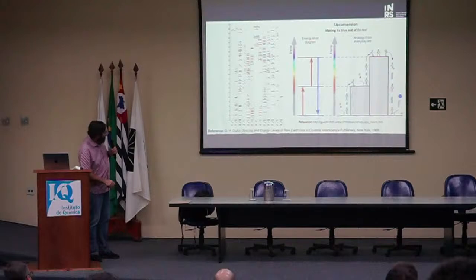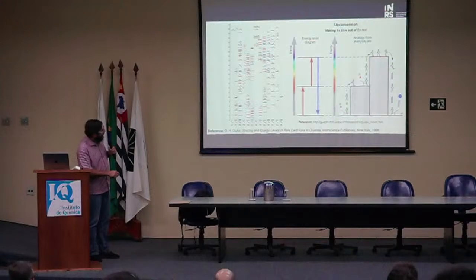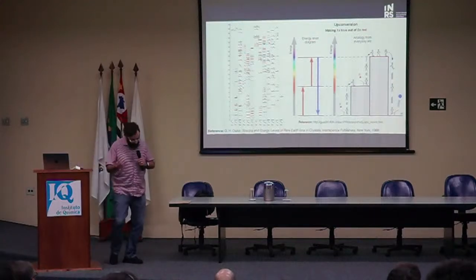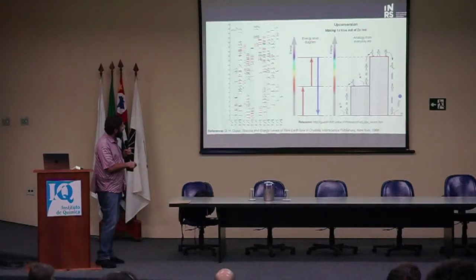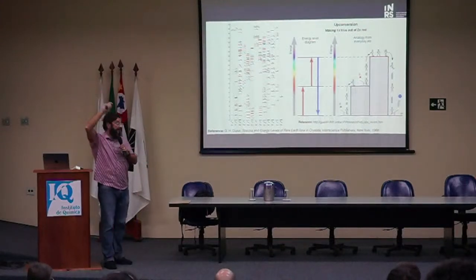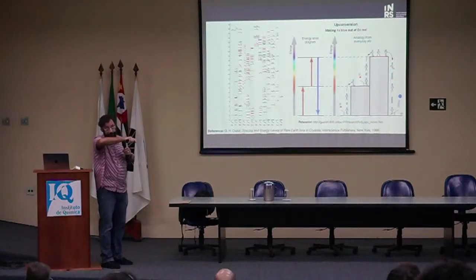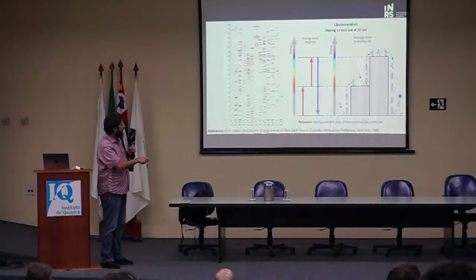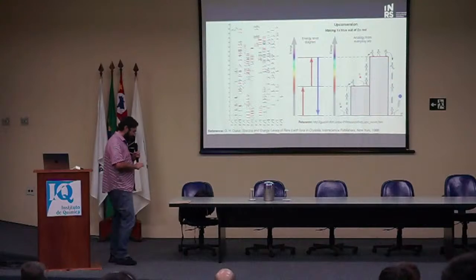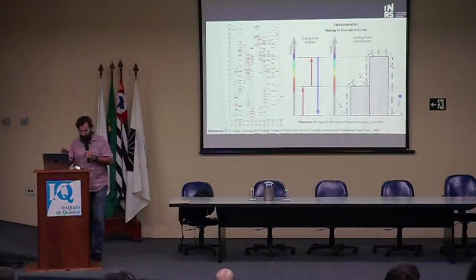Which means that you can use a near-infrared laser to populate this upper state, right? So you have one near-infrared photon come in, and it basically excites the ion through ground state absorption from the ground state to this state. Because the lifetime of this state is long, typically milliseconds, hundreds of microseconds, there's a very high probability that a second incoming photon will propel you to that upper state. And then you emit a higher energy photon that's essentially equal in energy to these two photons. It's not always the case. It's a very, very simplified version of what we call upconversion, but that's the case.